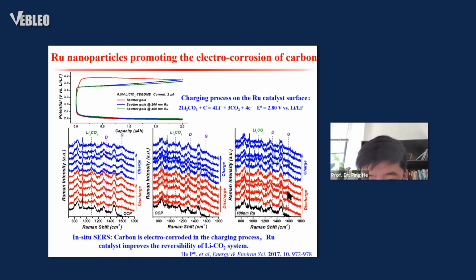During discharge the G band peak is enlarged, and during the charge process, the G band peak vanishes. So we can conclude that the carbon is electrochemically decomposed in the charging process. The ruthenium catalyst improves the reversibility of the lithium carbon dioxide system.